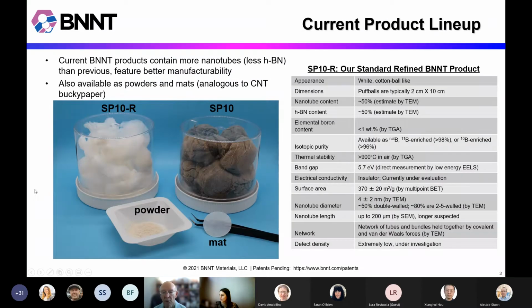Next slide. On the right side of this photo, I'm showing our standard product, SP10. This is the as-synthesized boron nitride nanotubes in what we call a puffball form. The dark color comes from the presence of some elemental boron, which is one of the two byproducts of our synthesis method. We can refine the material, as you can see here in this jar on the left side. It has a nice white appearance, and it contains about 50-50 boron nitride nanotubes and nanoscale hexagonal boron nitride.